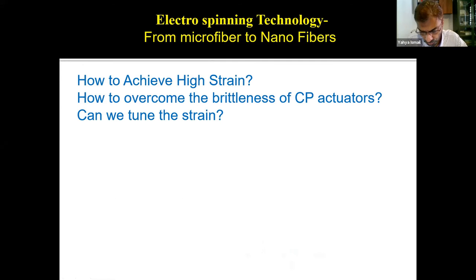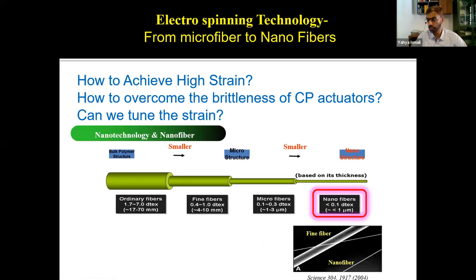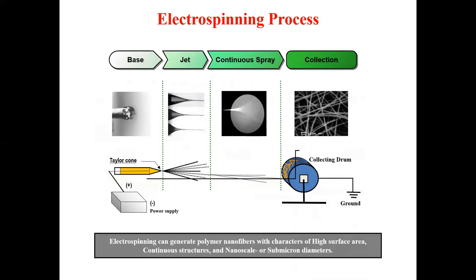The major focus of such studies, especially for engineers, is not on understanding the basic science, but on how to improve the performance. So how to achieve a high strain, how to overcome the brittleness of conducting polymer actuators. What we did is move from microfiber technology towards nanofiber technology through electrospinning. So we are getting finer and finer fibers at the nano level. And then we were able to produce through electrospinning either a nanofibrous mat, an aligned nanofibrous mat, or a single nanofiber or a combination of one or two nanofibers.